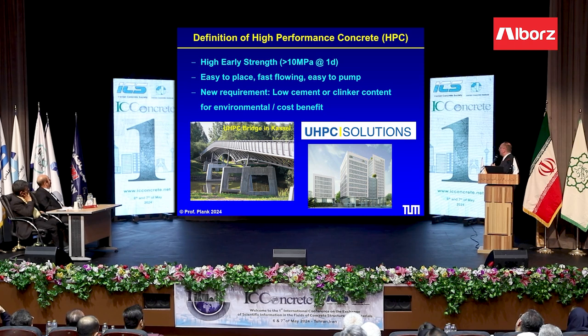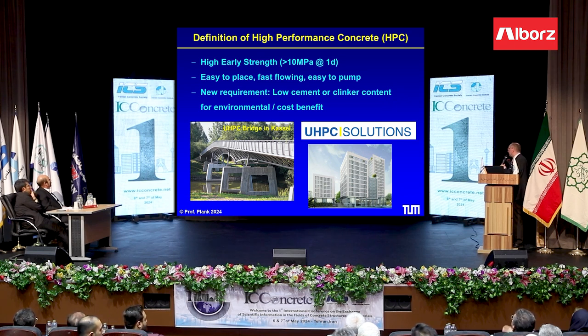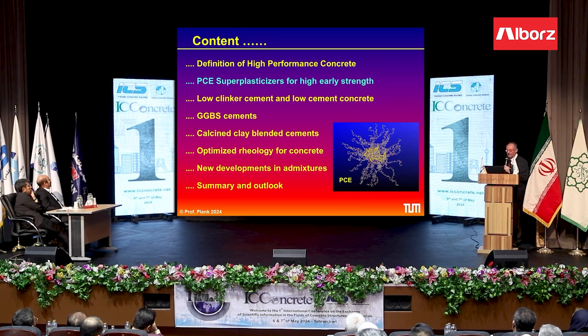High performance concrete we define as a concrete which reaches very high early strength within a day, actually ideally within 16 hours, 10 megapascal, and the final strength has to be beyond 60 megapascal, like 100. And at the same time, it should be easy to place, fast flowing, and also easy to pump. And I will talk especially about this because this is not so easy to achieve in such a concrete. And a new requirement is that it should have a low carbon footprint because of a low cement content or a low clinker content. And this is not easy to achieve.